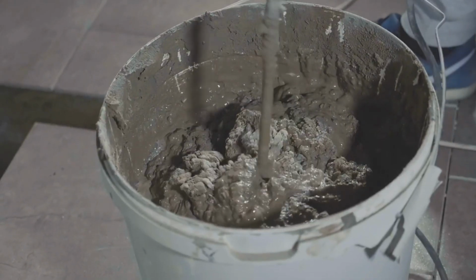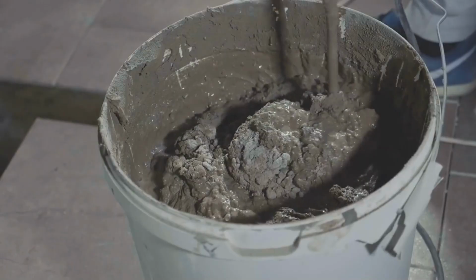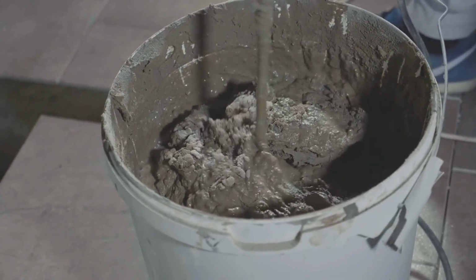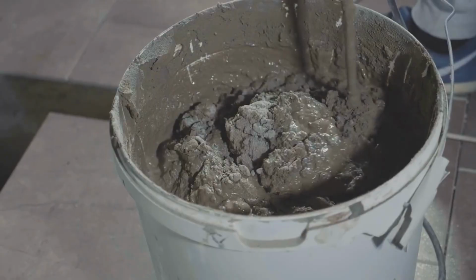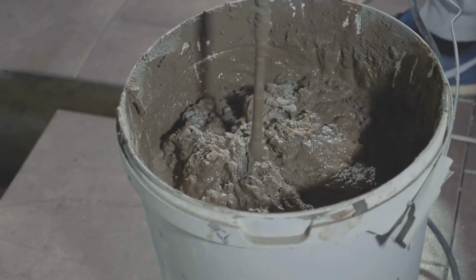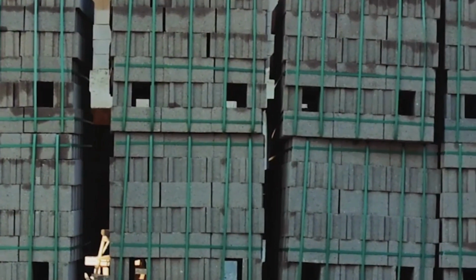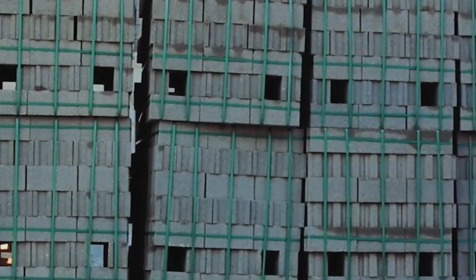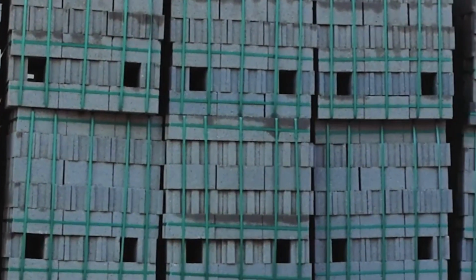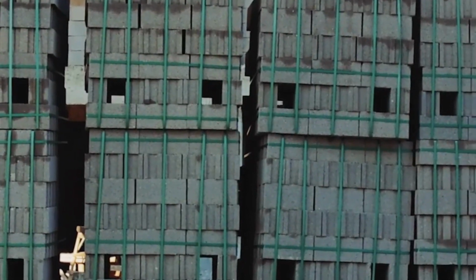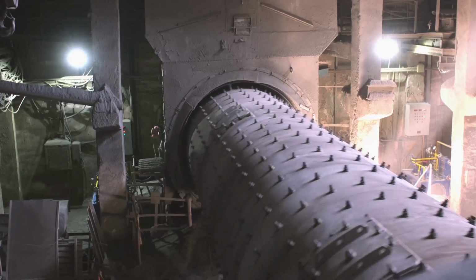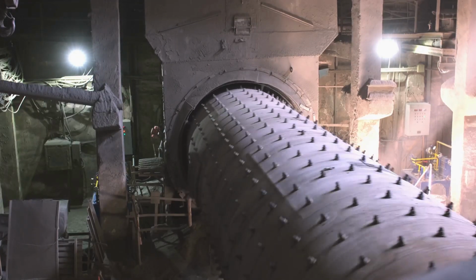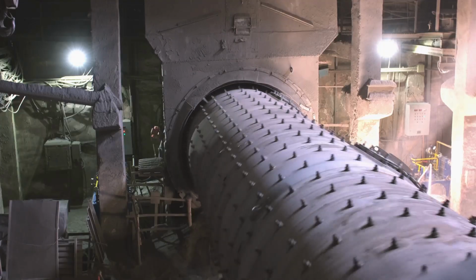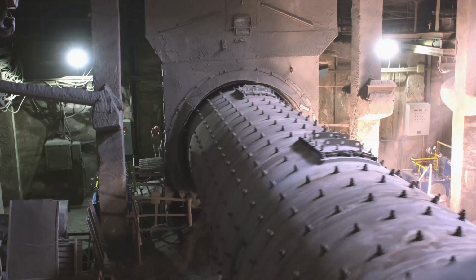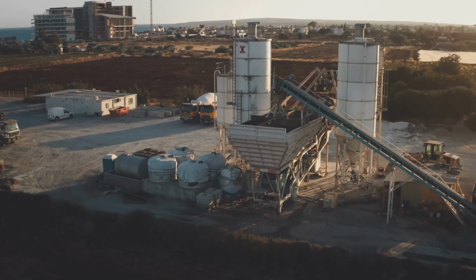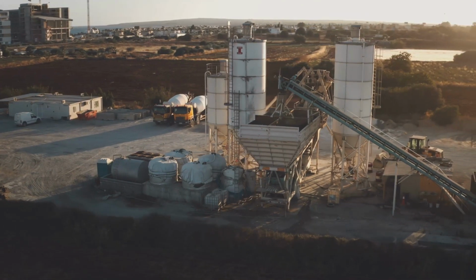Making clinker, the essential binding agent in modern Portland cement, requires heating limestone and other materials to temperatures exceeding 1,450 degrees Celsius. After years of incremental gains, the industry has discovered that the fundamental physics and chemistry of this process offer no more easy efficiencies. The energy penalty is simply too high, and the associated carbon dioxide emissions are staggering. From the fuel burned and from the chemical breakdown of limestone, together they account for roughly 8% of global emissions.